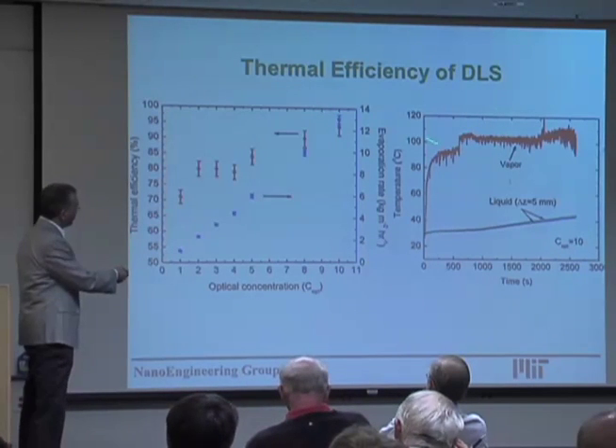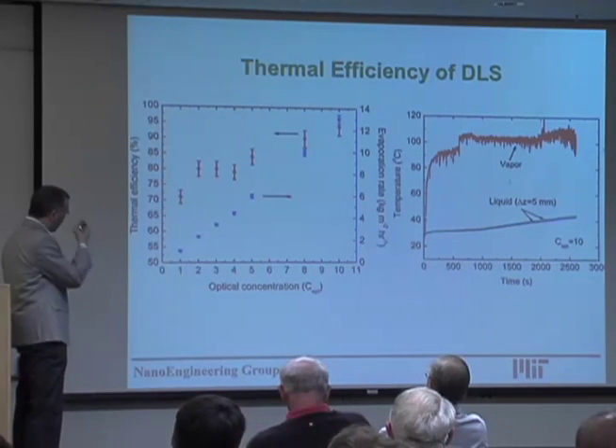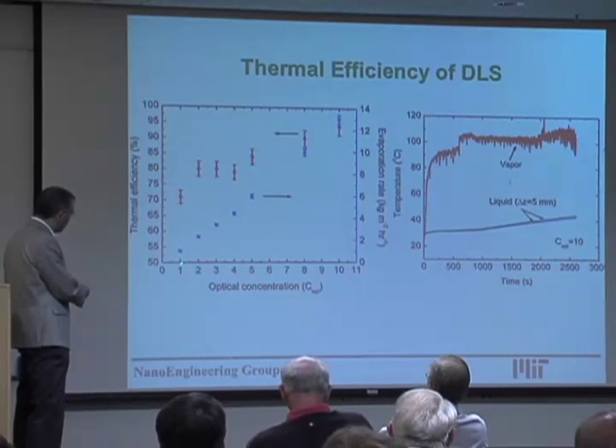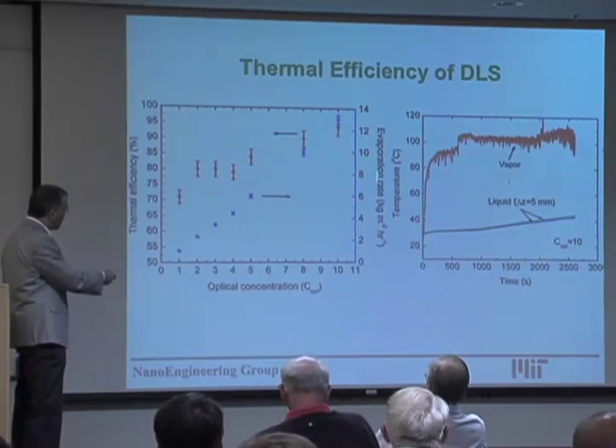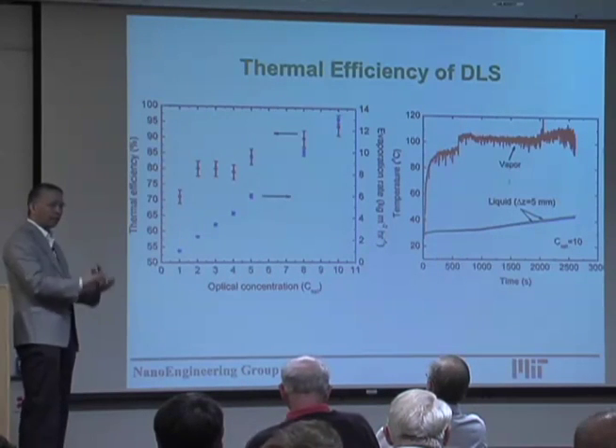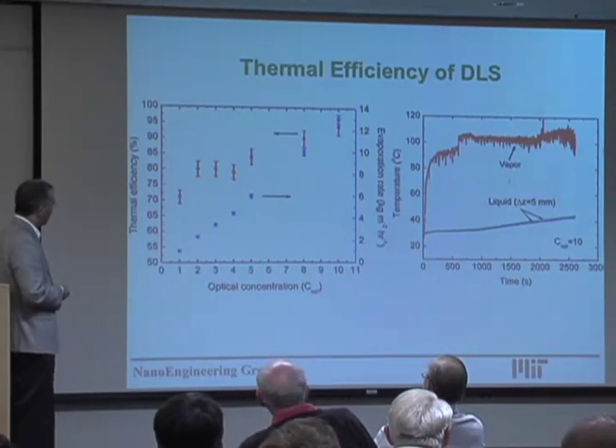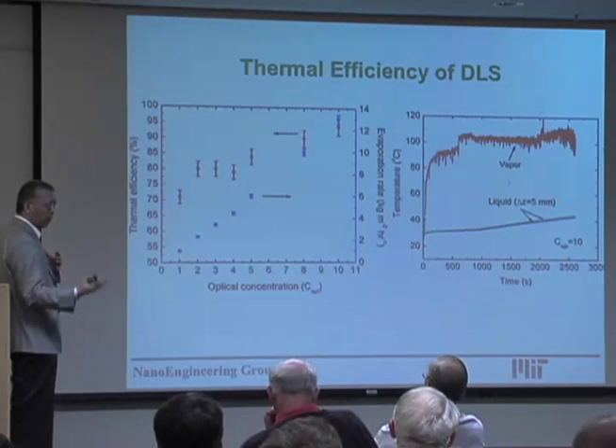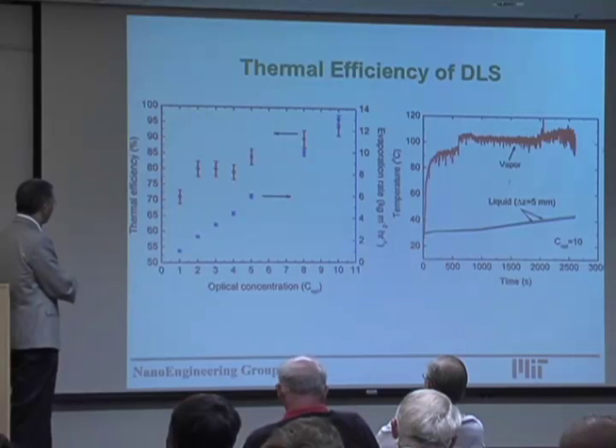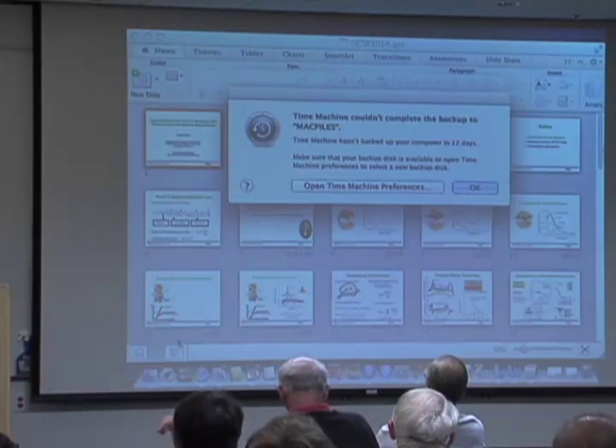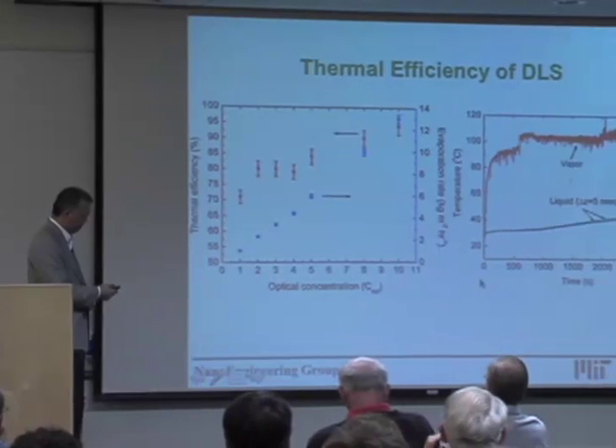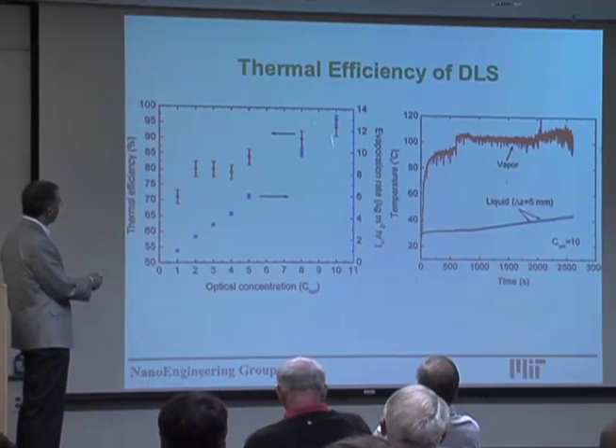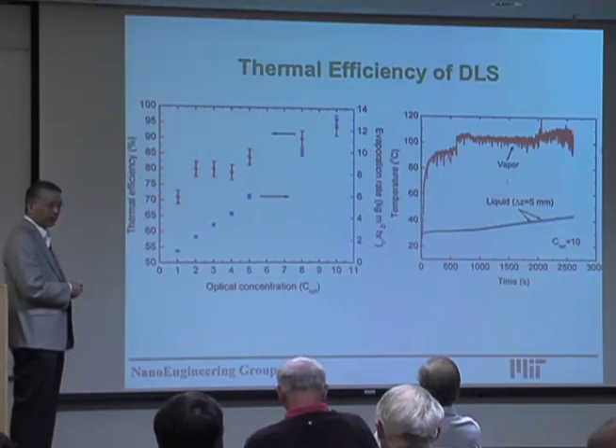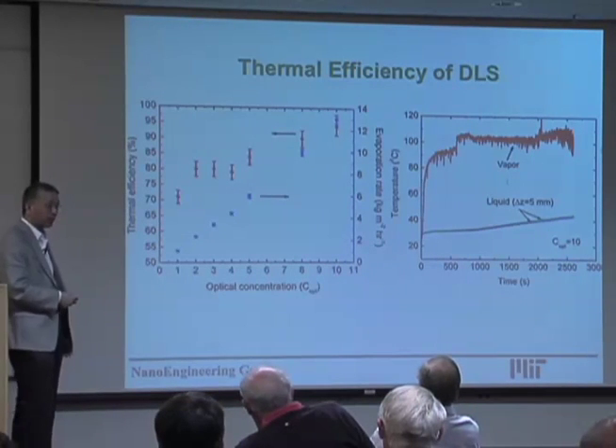So this is a double layer structure, and here is the optical concentration. This is one sun, and we measure the rate of evaporation. From that, we know how much energy is going into steam or vapor, and we also know how much solar radiation comes in, so we can calculate the efficiency. And here is the efficiency. You can see that the efficiency we achieve is over 90%, under 10 sun conditions.